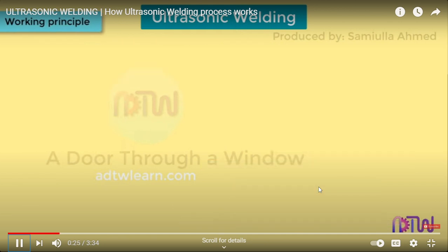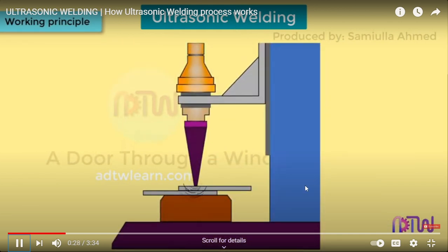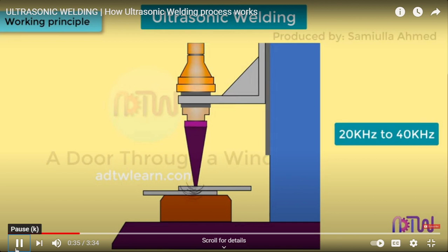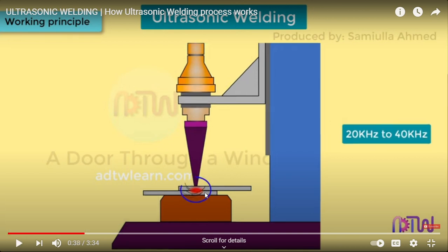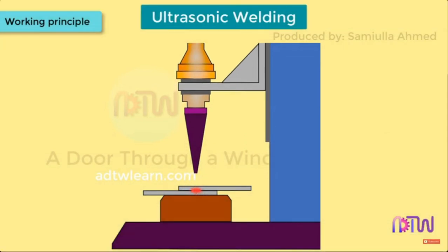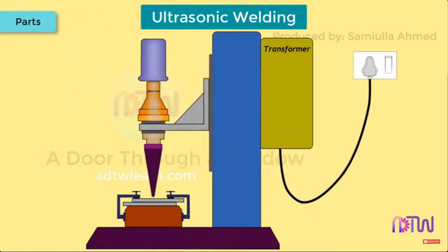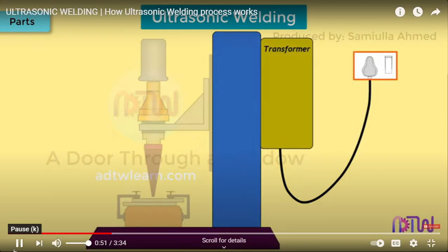Working principle from the video: the weld is produced by application of high frequency ultrasonic vibrational energy in the order of 20 to 40 kilohertz (in some references 15 to 60 kilohertz). This causes localized heating at the point of contact between the two work pieces, producing a metallurgical bond without melting the metal.